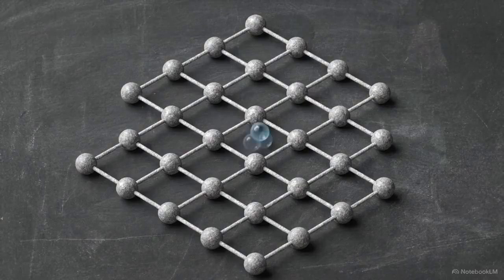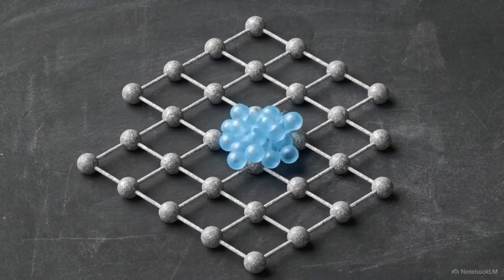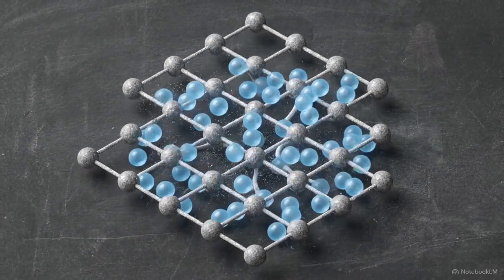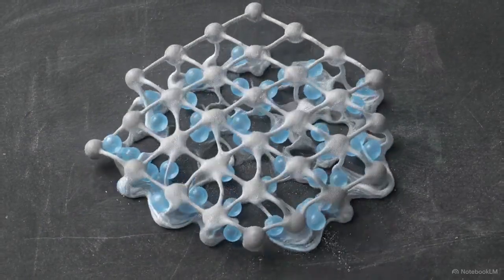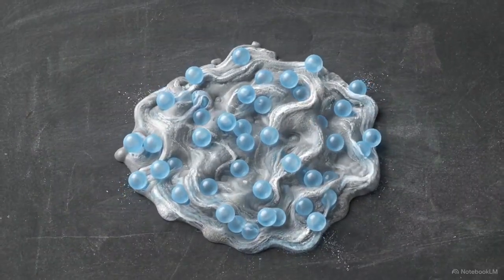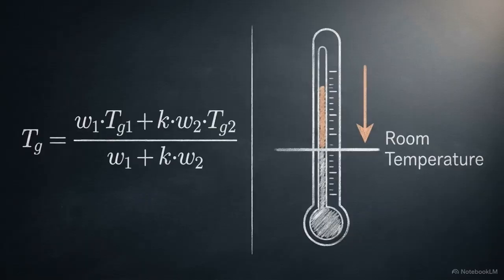When these mobile water molecules infiltrate a rigid, glassy lattice, they force the polymer chains apart. The structure collapses, softening into a fluid, rubbery mass. Described by the Gordon-Taylor equation, mixing water into an amorphous solid drastically lowers the total system's glass transition temperature, dragging it down toward room temperature.